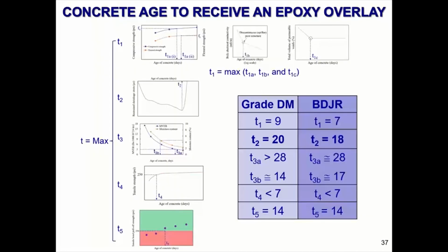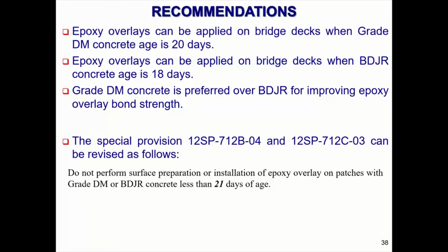So this is the results of all of the tests. You can see that for grade DM, you shouldn't put the thin polymer overlay on the concrete at less than 20 days old. And for the BDJR, you should not put it on the concrete at less than 18 days old. So the recommendations from the research project that they're going to be giving to MDOT: epoxy overlays can be applied on bridge decks when grade DM concrete is 20 days, like I said, BDJR 18 days. And they are indicating that grade DM is giving us better results overall and over time.